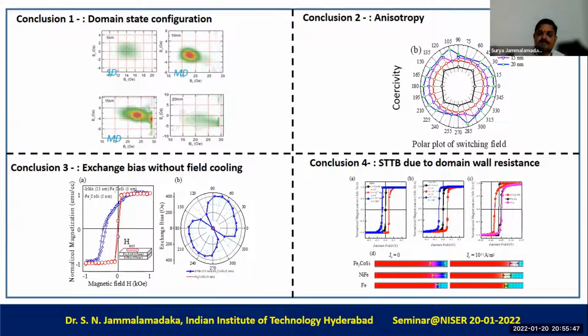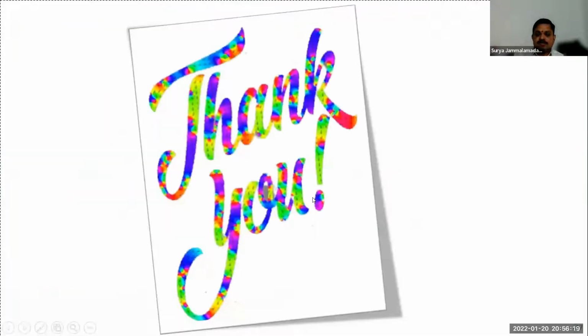infinitely long wire. So indeed, it is not only specific to Fe2CoSi, but we could able to show the spin transfer torque bias phenomenon in other systems like permalloy and iron sample. The variation in the spin transfer torque bias from one ferromagnetic system to other ferromagnetic system has been attributed to the domain wall width. As the domain wall width is smaller and smaller, the domain wall resistance will be high, which leads to higher spin transfer torque bias. With this, I would like to thank for your attention. Now the questions are welcome from the audience.